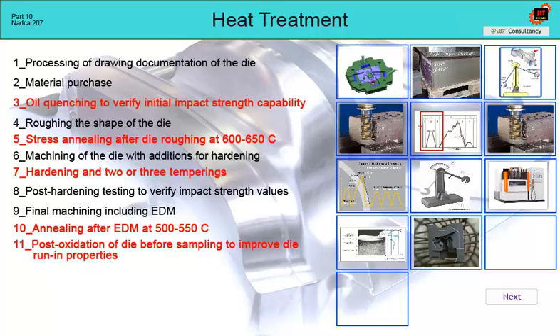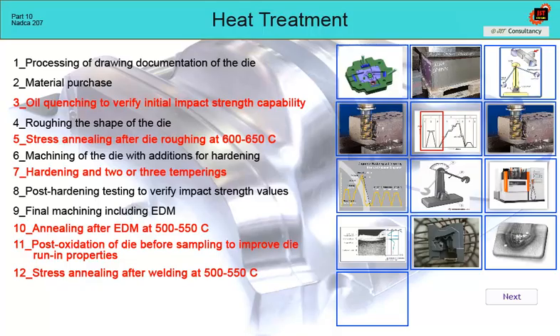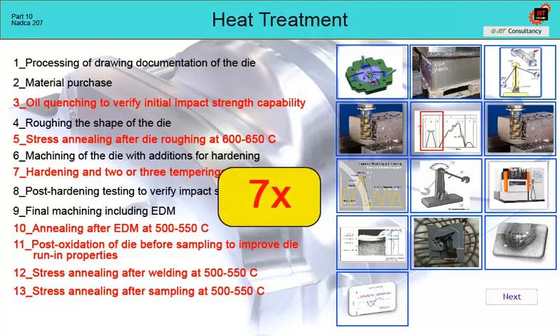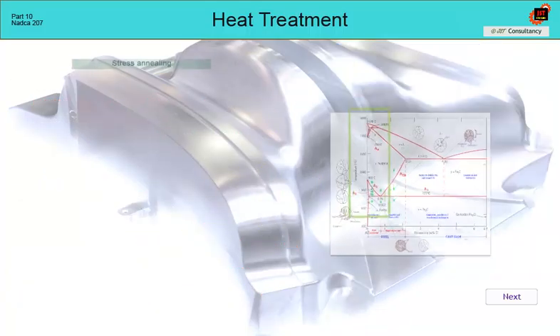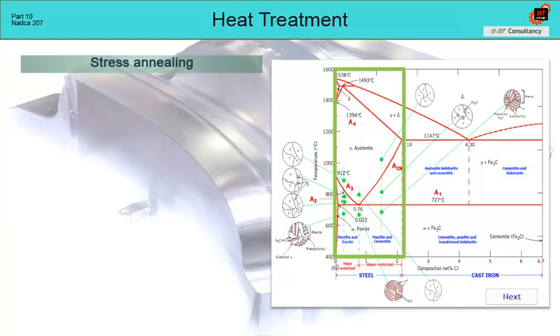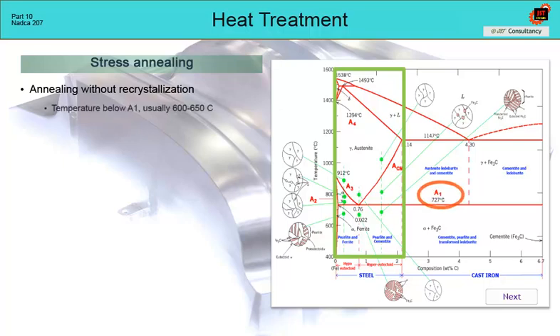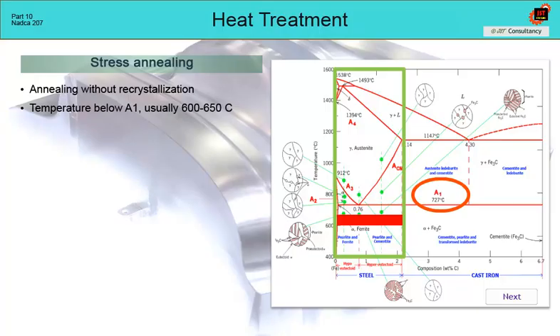In case of shape correction, annealing after welding at 500 to 550 Celsius, annealing after sampling to remove thermal fatigue stress. Therefore, each insert for a high-pressure die should go through the heat treatment plant up to 7 times. The first thermal operation is annealing to remove stress after roughing. This is annealing without recrystallization at a temperature below A1. Usually, it is a temperature of 600 to 650 degrees Celsius.